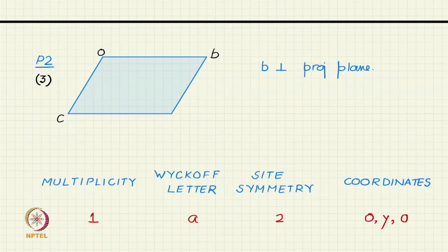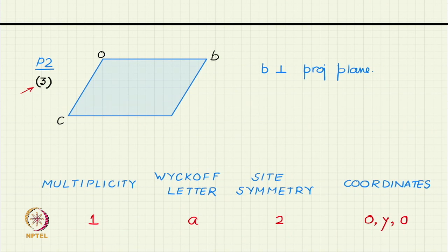So, for example, I am taking space group number 3. As you can see, it is one of the very early space groups in the table of 230 space groups, and this one is a monoclinic space group, monoclinic crystal system. So, that requires only a two-fold, as you know, and you can see from the Hermann-Mauguin symbol that this has a generator just a two-fold. So, the capital P stands for primitive lattice. So, that means the lattice is primitive.